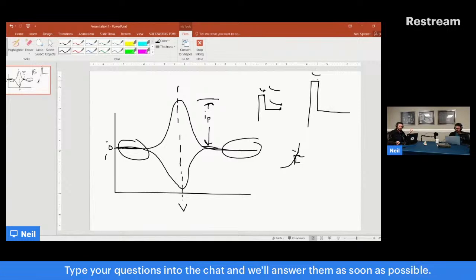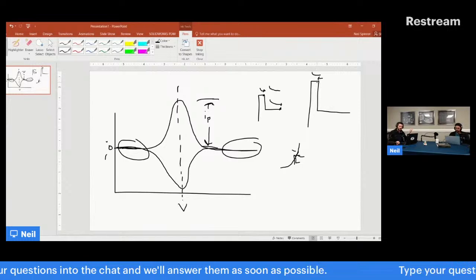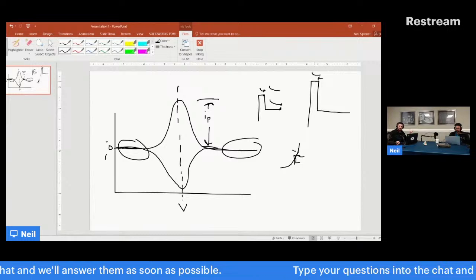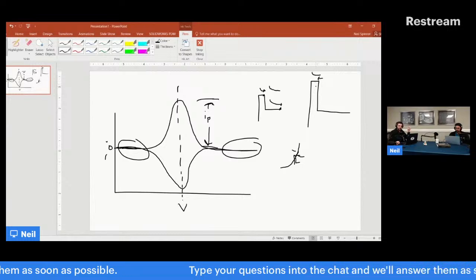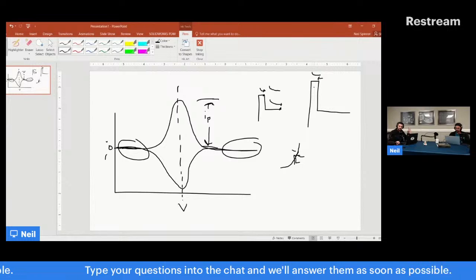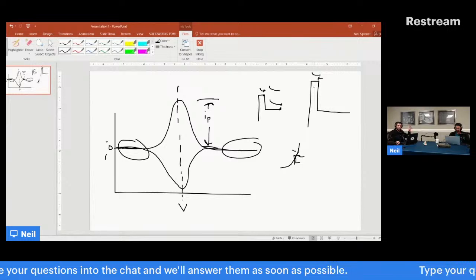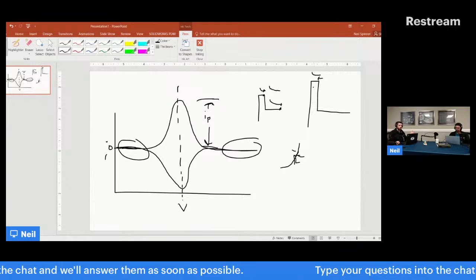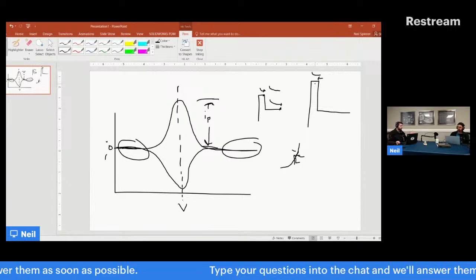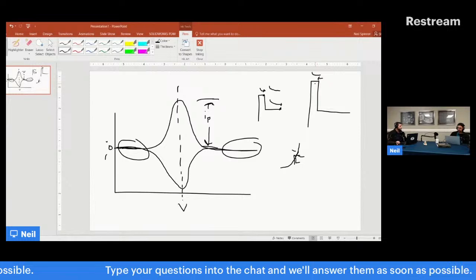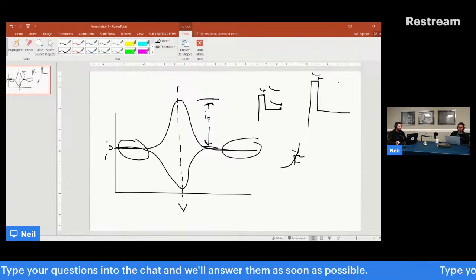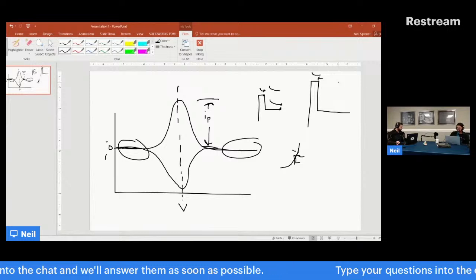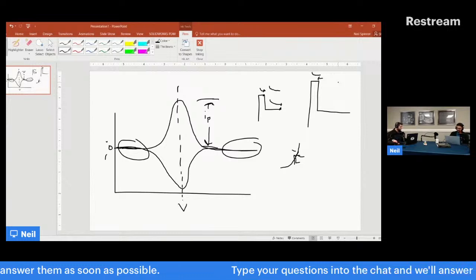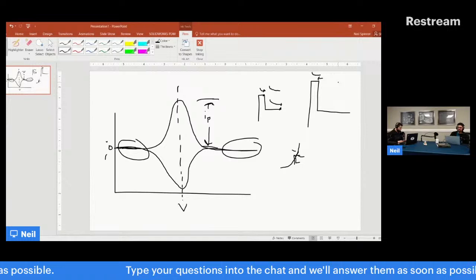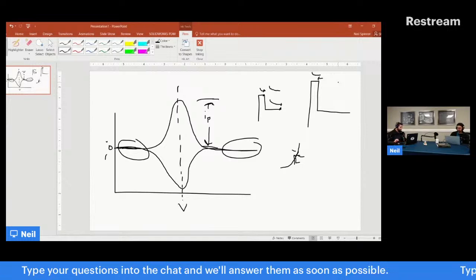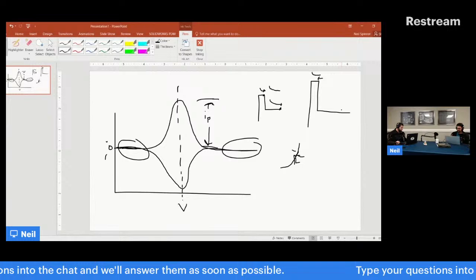Sometimes what you're trying to do is modulate this time to be as short as possible. Sometimes you're up against it because the duration of this pulse has to be the minimum the potentiostat can do, sometimes a millisecond or less, or 100 microseconds. I only know this because I've been hammering away at chronoamperometry for a while. I almost look at this as little chronoamperometry steps, except we're subtracting different ones.